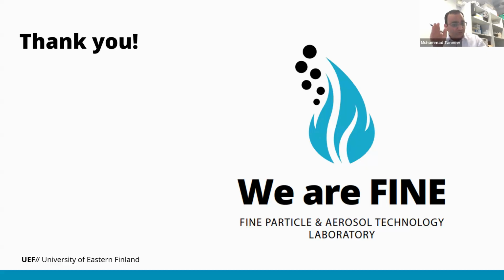As you have seen in the McKenna burner also, they have tuned the combustion conditions there. By controlling the equivalence ratio, they can tune the band gap of the particles. So this is all about controlling the parameters. If you are using a simple sooting condition, then controlling is not so effective. But it is possible if you can control the parameters there. This is the reason that in flame spray pyrolysis we have the opportunity to play with different parameters to adjust the combustion condition to maintain a particular particle size and features in our system, so that we can have a particular kind of particle. But for normal systems, it is quite difficult.